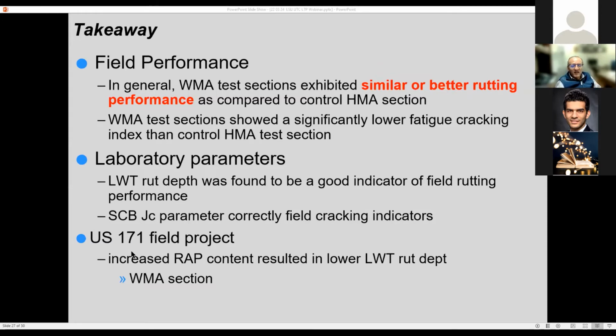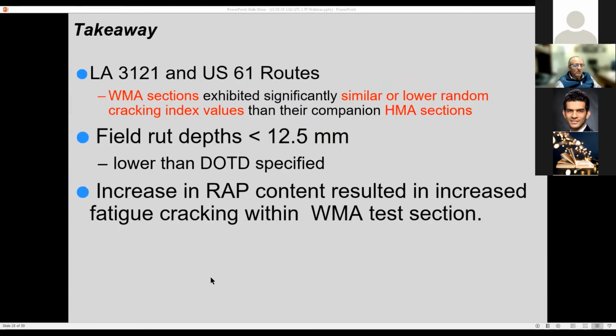In some additional observations, we saw that an increased RAP content resulted in lower LWT rut depth in the WMA section. And this is again possibly due to the layer underneath the top, so it's more of a structural issue rather than a material issue. And on the LA 3121 site, as well as US 61, the WMA section basically showed lower cracking than its counterpart in the HMA section.